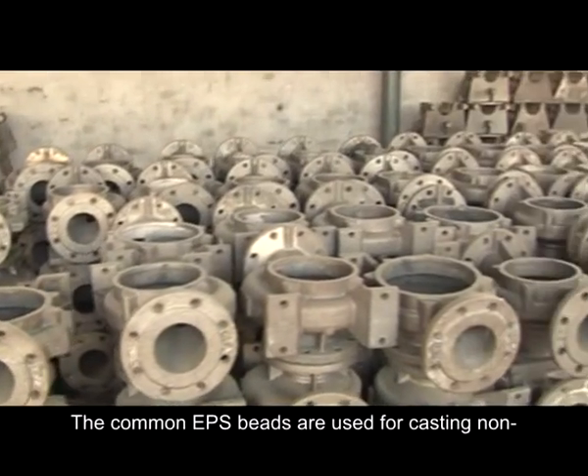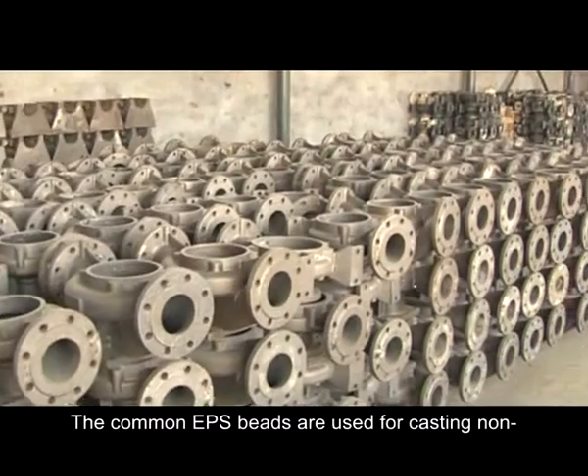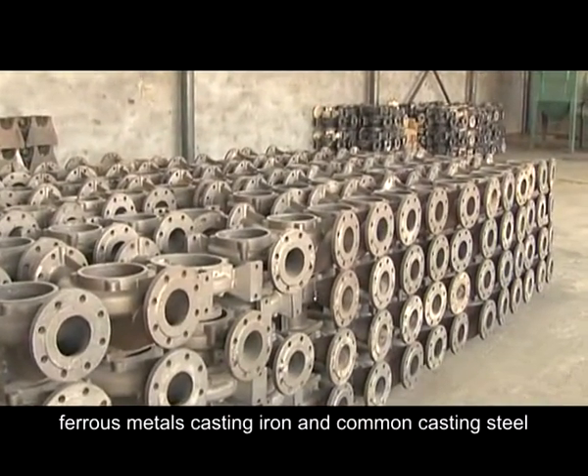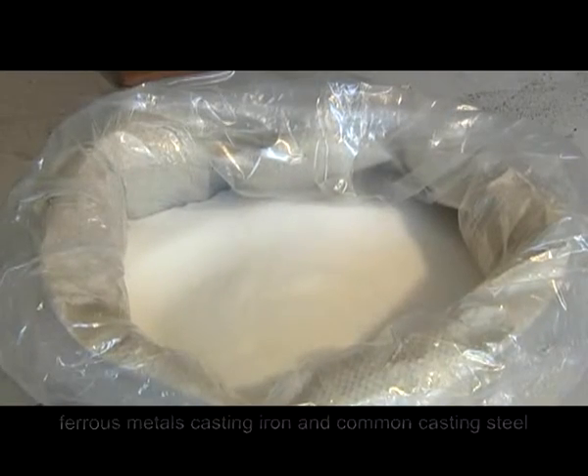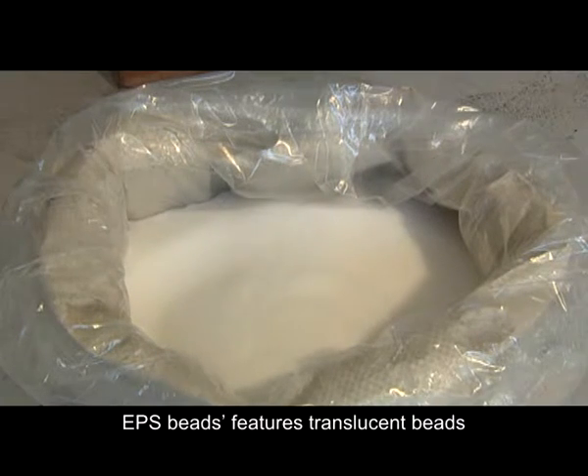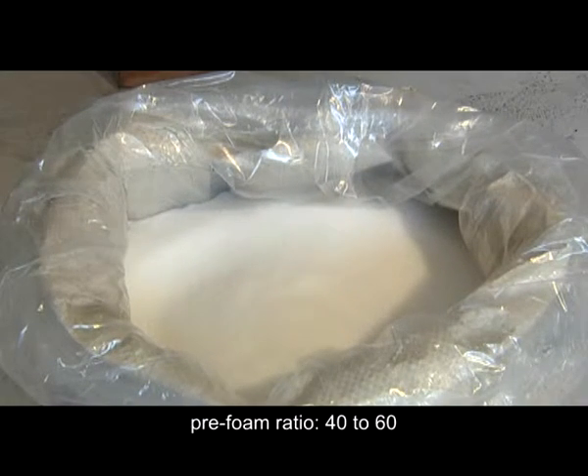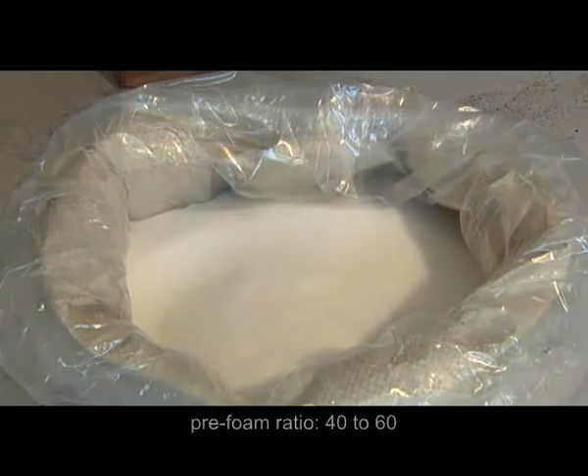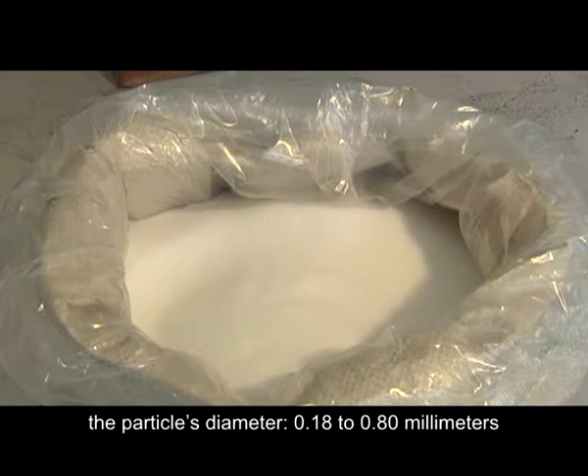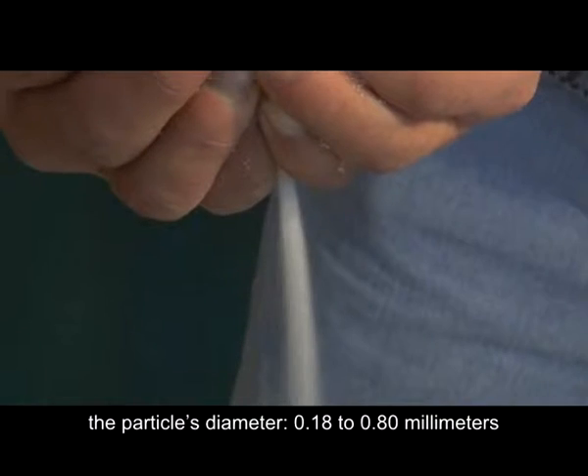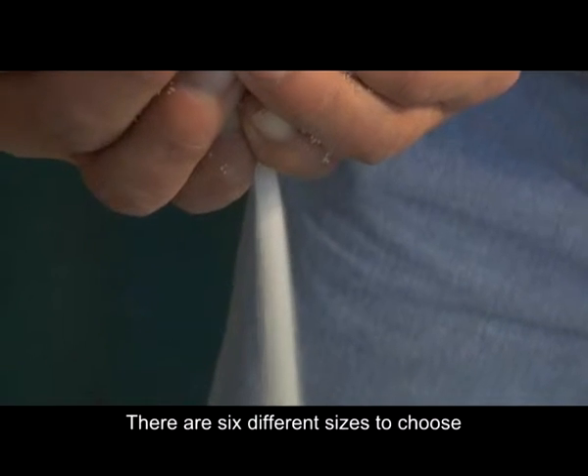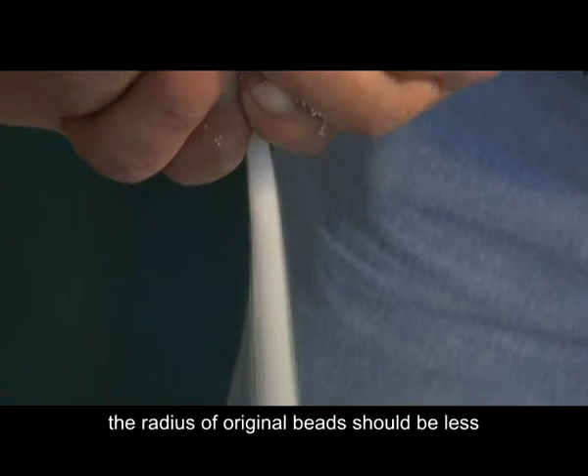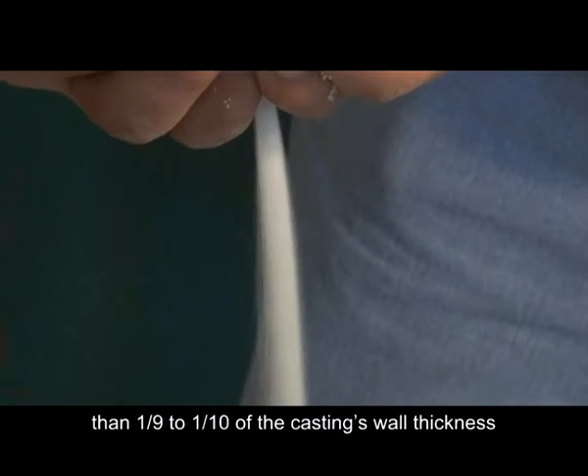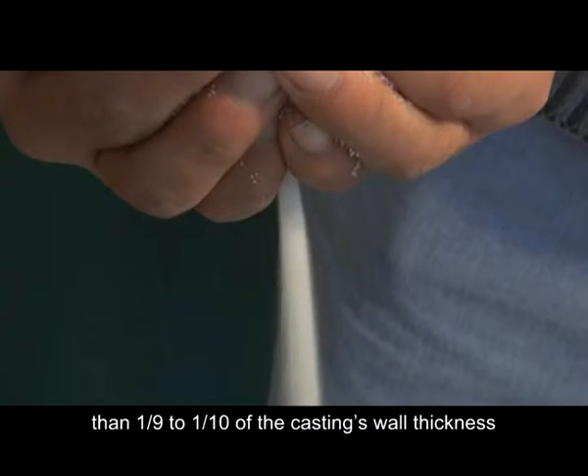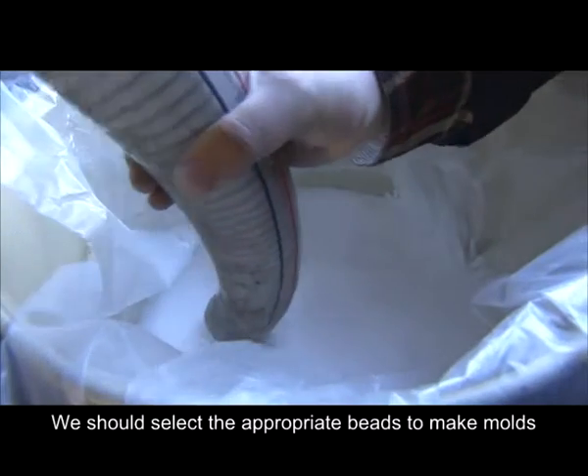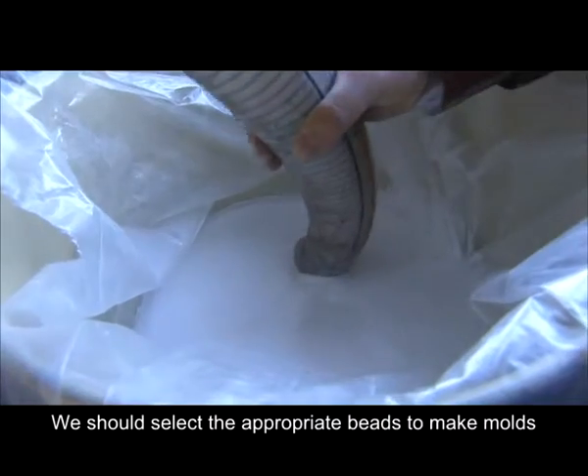The commonly used EPS beads are used for casting non-ferrous metals, cast iron and common cast steel. EPS beads feature translucent beads, pre-foam ratio 40 to 60, and particle diameter 0.18 to 0.80 mm. There are 6 different sizes to choose from. The radius of the original beads should be less than 1/9 to 1/10 of the casting's wall thickness. We should select the appropriate bead to make molds.